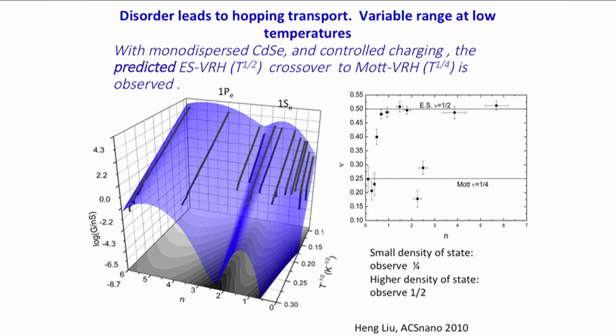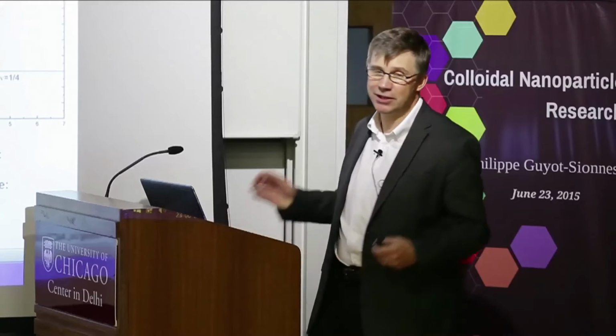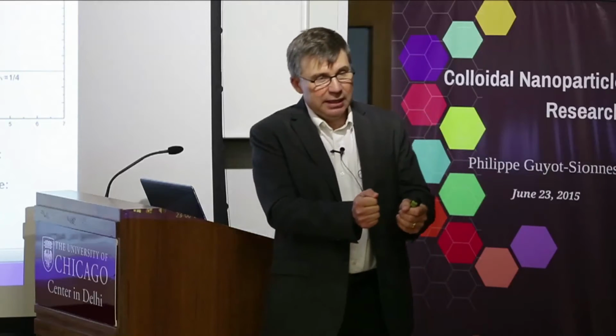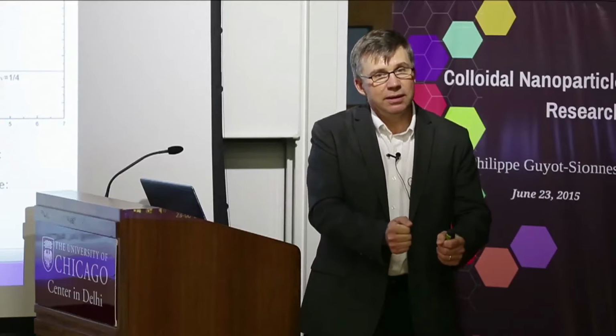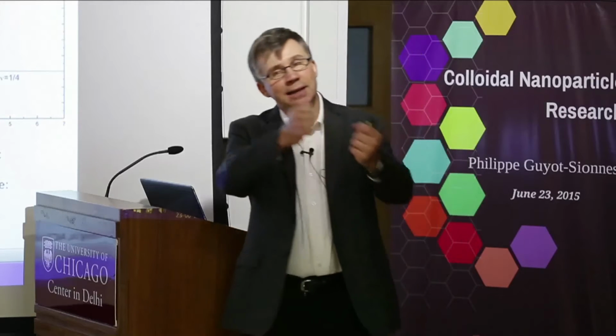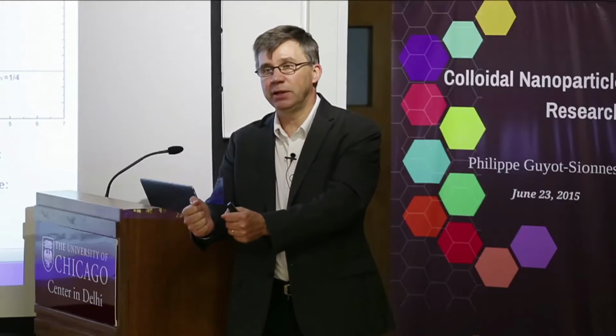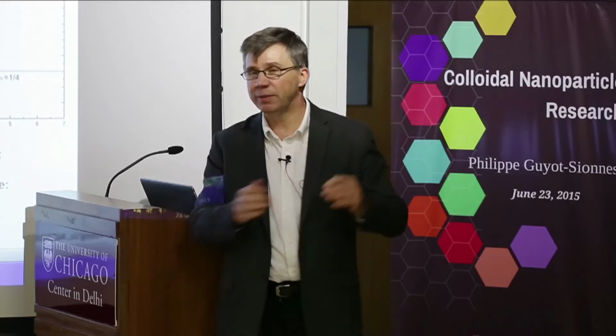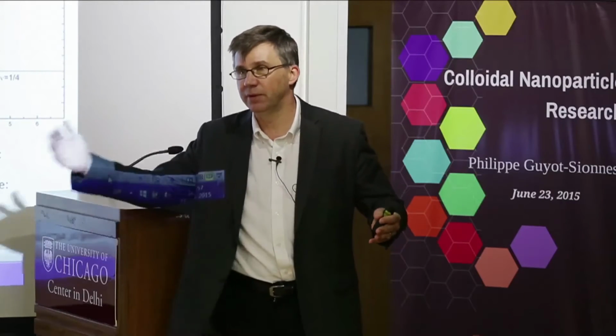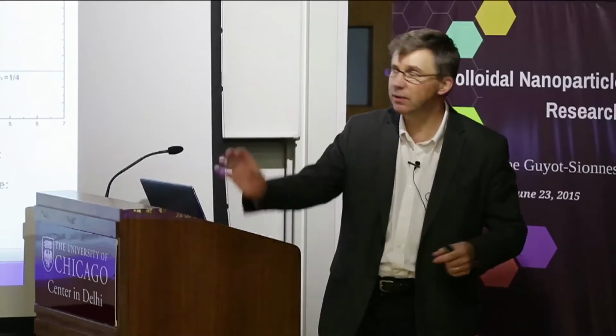In our systems, and in all the systems that show fairly low mobility, the transport is definitely a hopping transport. It is not the solid state physics level of transport where you have band transport. It's hopping, so the electron is in the particle. It's thermalized to its lowest level. It becomes thermally activated to hop onto another particle. It thermalizes again, so there's absolutely 0 coherence between hops. It's really just total classical hopping.